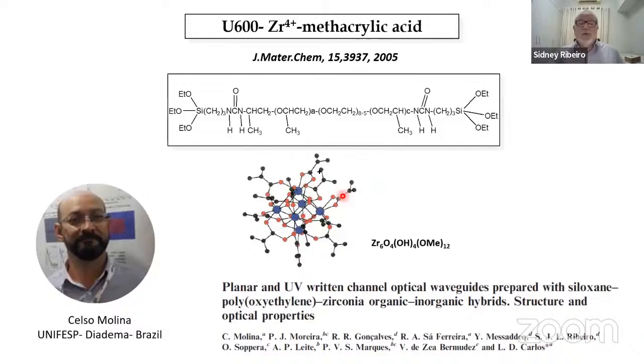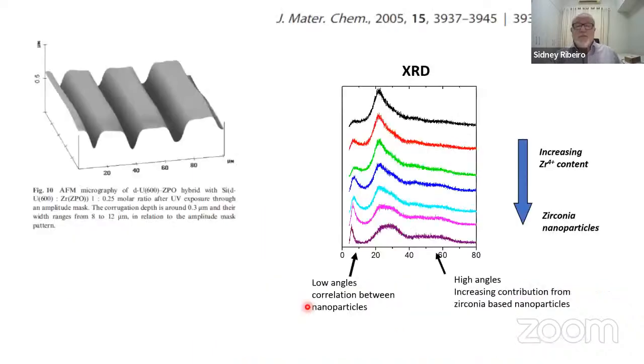We did that some years ago. This is an organic-inorganic hybrid that was cited last week by Ruth Ferreira, our colleague from Aveiro. And we used this hybrid together with our functional group in order to have materials in which we could write optical waveguides and gratings with UV light. These are some results of that paper some years ago with the gratings and the increase in the zirconium nanoparticles content, as we increase the zirconium content, obtained by X-ray diffraction.